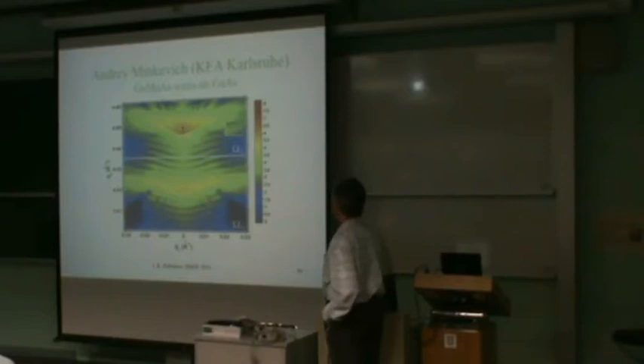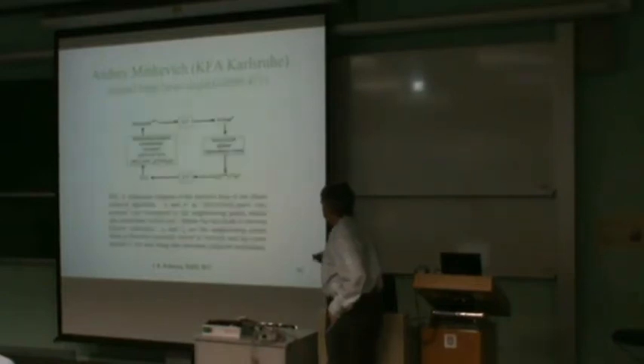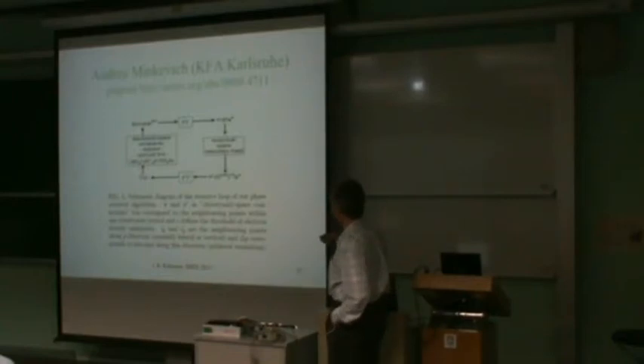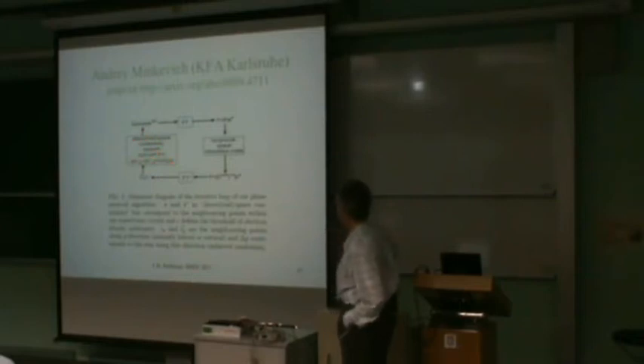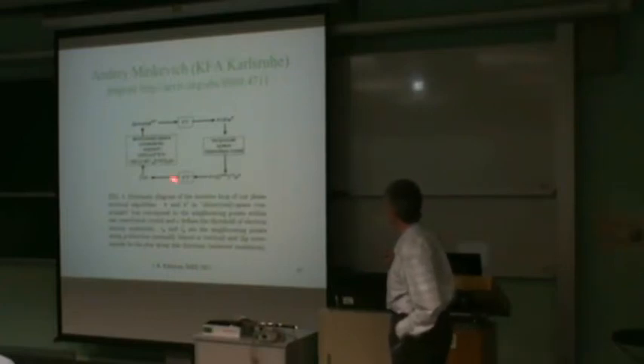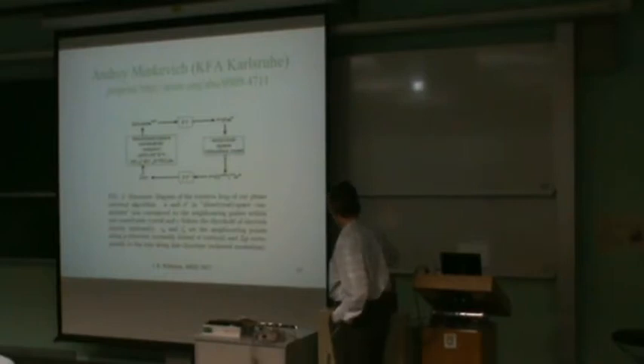And in the case of the Minkevich experiment, the sample was small enough that it fit entirely in the beam of the experiment. I won't go into the details here, but this was the algorithm that he came up with for constraining the real space, but in such a way that allowed the phase to track, but didn't overly constrain the problem otherwise. And the reciprocal space is the same as the method that we use and everybody else uses.